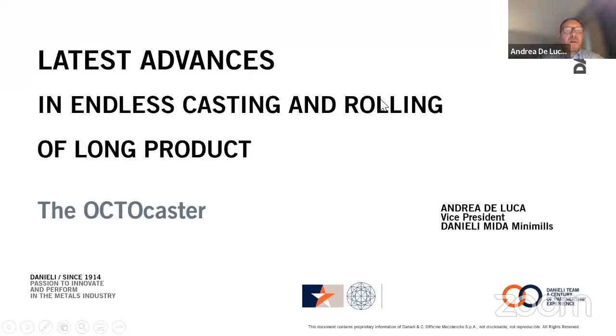Yes. One was a very big surprise for us too. Let's say the small crack population, because the quality of the rebar is good, even with some small defects being acceptable. But with the octagon, we saw all these small defects disappearing, thanks to, as I mentioned, the quality of the first pass rolling and the benefits in the pass design. And thanks to these results, we moved to more difficult steels like peritectics and also high carbon steels.